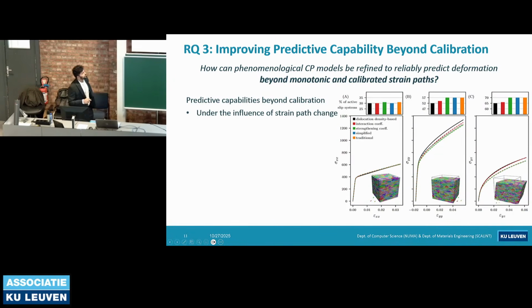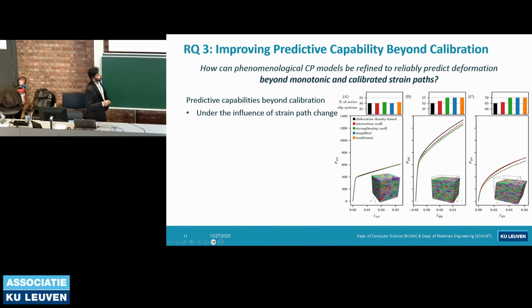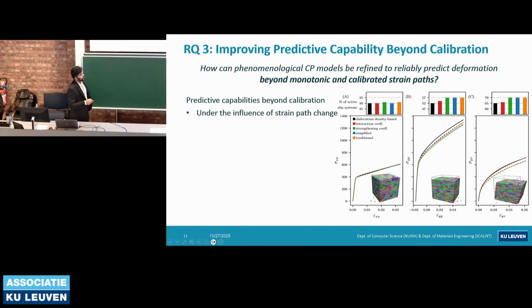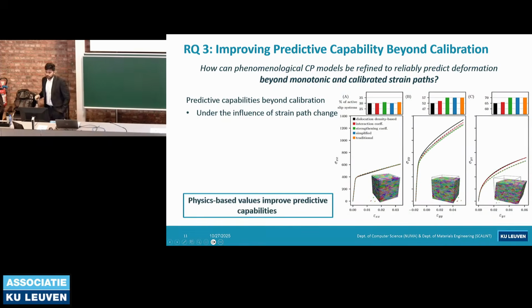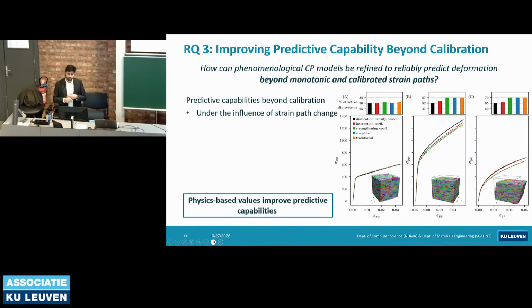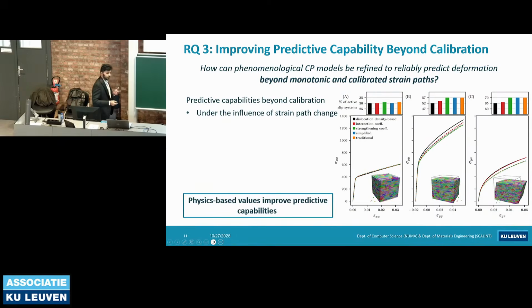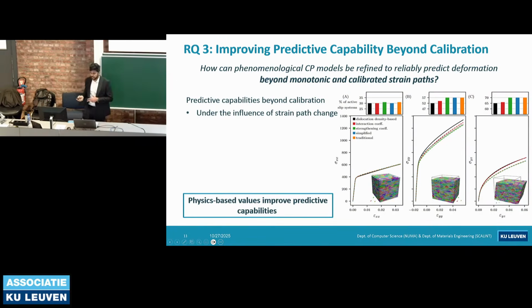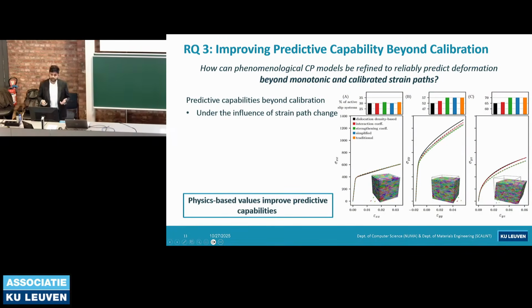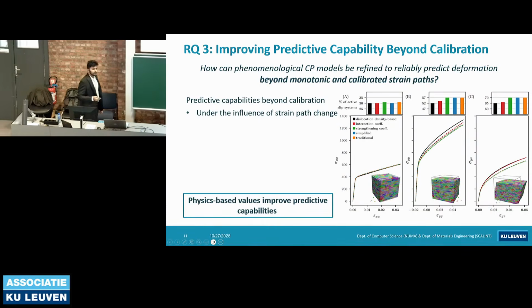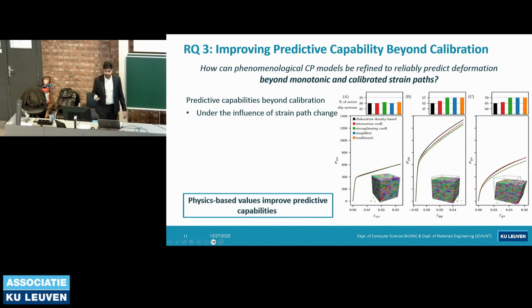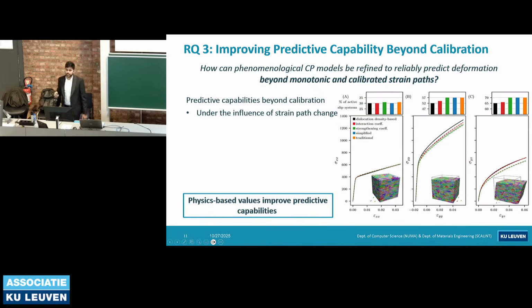Here we activate about 65% of the total active slip systems, and here we also see that the interaction coefficient yields a better response in comparison to the traditional. So we compared it against multiple fronts, one within the data domain of calibration and even outside, and we saw that the physics-based parameterization with the values obtained from lower scale simulations yields better results and therefore demonstrates predictive capabilities.